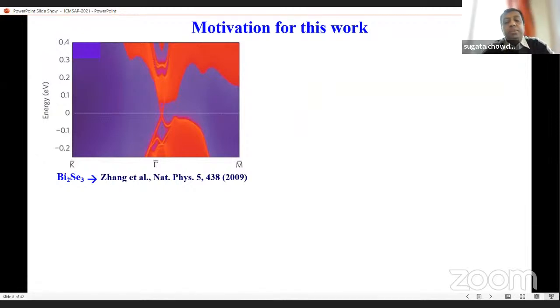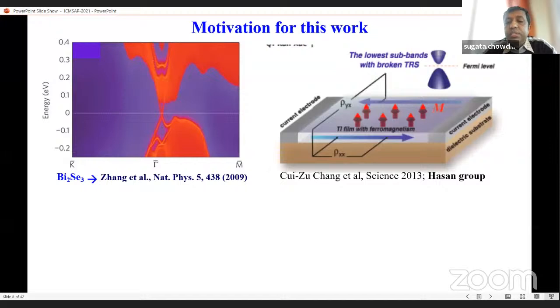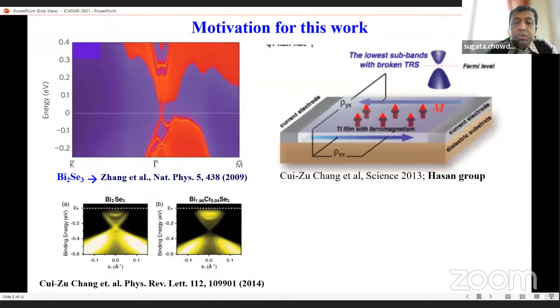So what happened after the prediction of the bismuth selenide structure? Zahid Hasan's group developed a method. They doped the system with magnetic atoms, and they observed the topological quantum anomalous Hall effect. Another group also doped the system with chromium atoms, and they also noticed that the band gap opens, so it is behaving like an insulator.